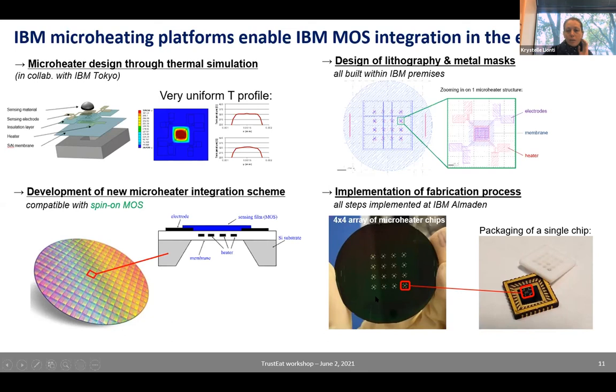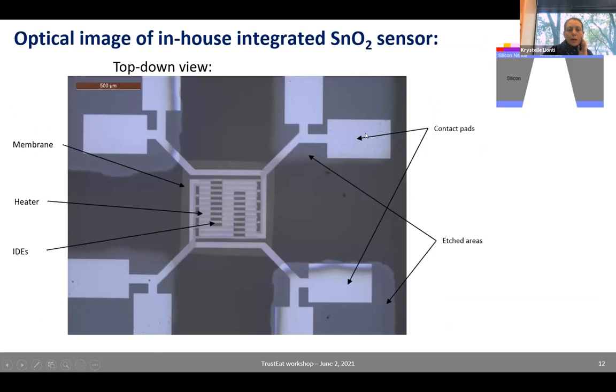On this slide, I'm showing a close-up of one device. This square that you see at the center is our suspended membrane. It is about 2 microns thick. On top of that, we have the serpentine here, which is the heater. Then we deposit an insulating layer, and then we have interdigitated fingers that you can see here, which are going to be the sensing electrodes for the MOS material.